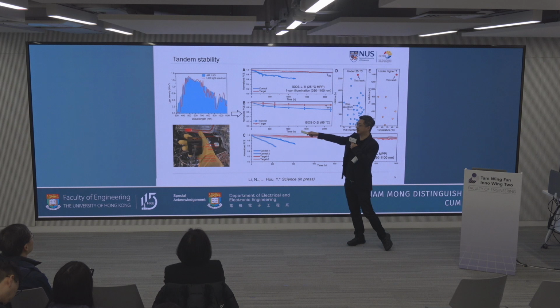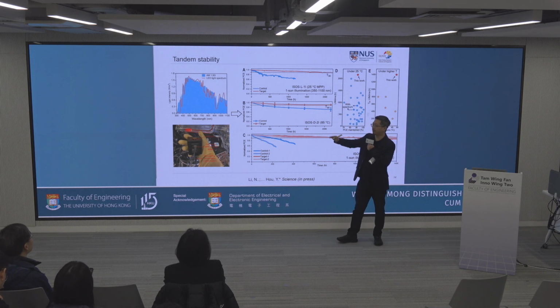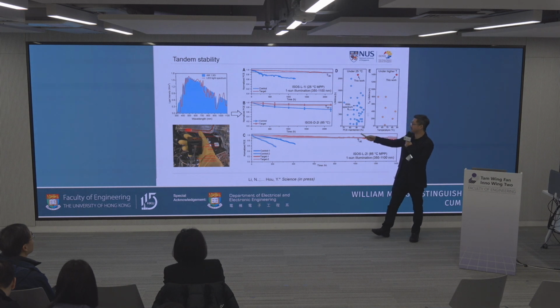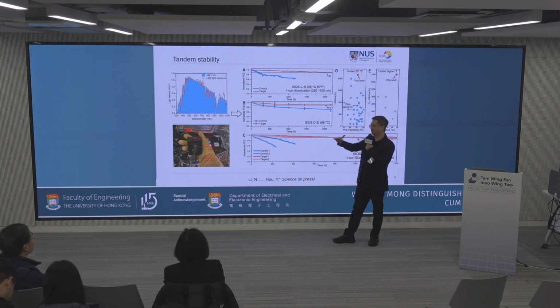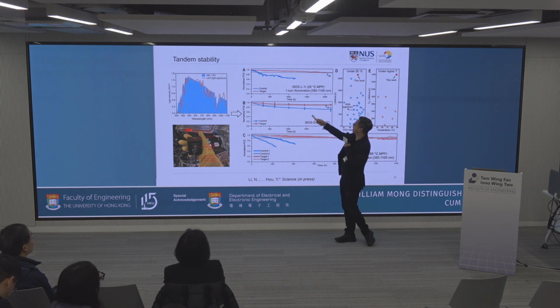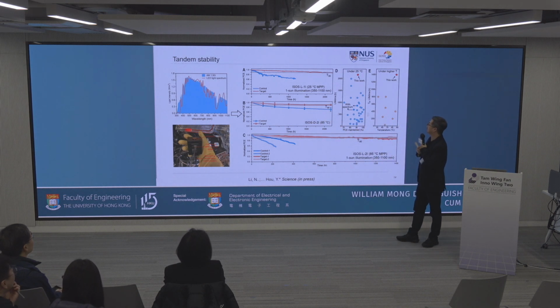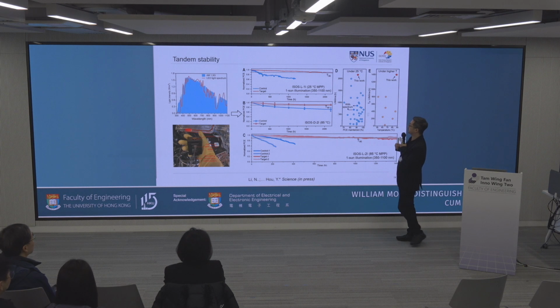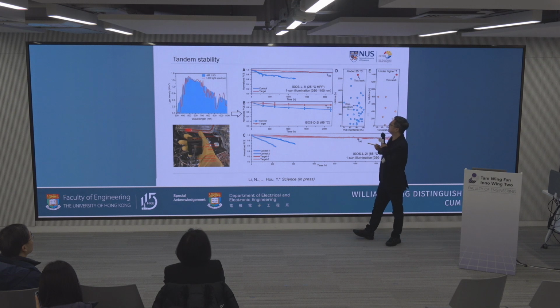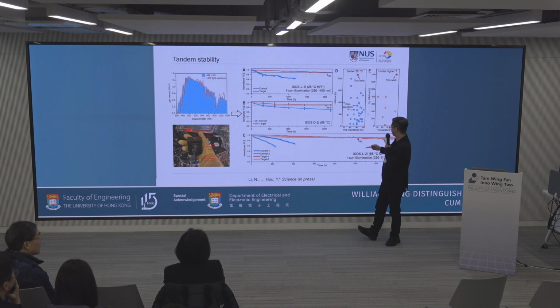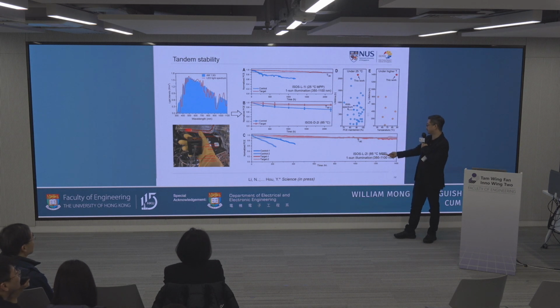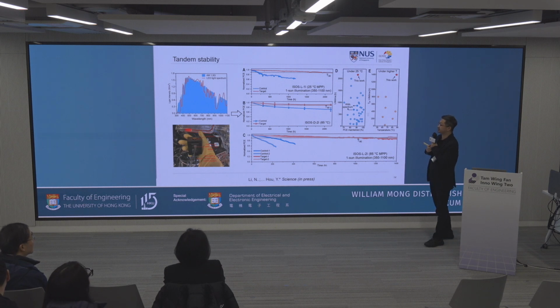It's LED based, and so the light source can last for a very long time, because for the stability measurement normally it's about thousands of hours. So you need to operate this high quality light source for a very long time, and this gives us quite good stability, and we basically tested two conditions. One is room temperature MPP, and this is quite okay, T90 is around 2,000 hours. Another one is 85 degrees MPP, which is a very challenging one previously for the perovskite silicon tandem. And here we can achieve T90 of more than 1,000 hours, and this is among the most stable perovskite silicon tandem.